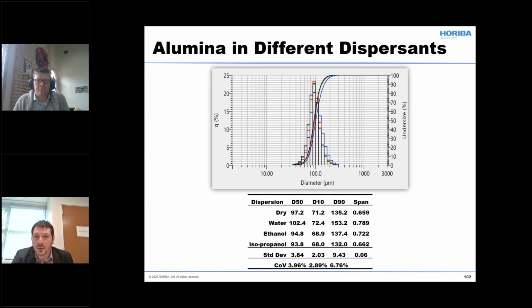So what would I go with? Of course, water, because you don't have the hassle of waste treatment, and it's cheaper. Or if you have the dry accessory, you can go ahead and measure the sample dry. Unfortunately, this is not the case for a majority of samples. Even though you found the main mediums that would be good to disperse the sample, it doesn't mean that using organic solvents like alcohol means you don't need a surfactant. For some metal powders, like this one that we measured, I didn't need to use one, but for some of them you still need a surfactant, even though you're using IPA as the dispersion medium. So it's something you definitely need to test.